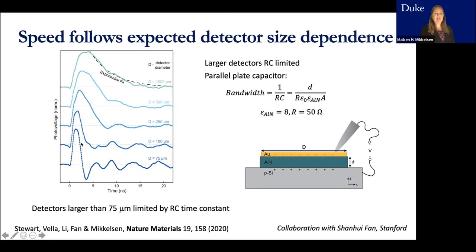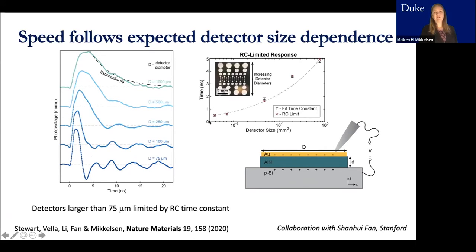But what's really exciting, I think, is that these larger detectors, yes, sure, they're limited by the RC time constant, but there's this regime of very small detectors to try to figure out what the limiting factors are, because right now we're limited by the instrument response. And we can see that the speed here as a function of detector size follows the expected behavior.